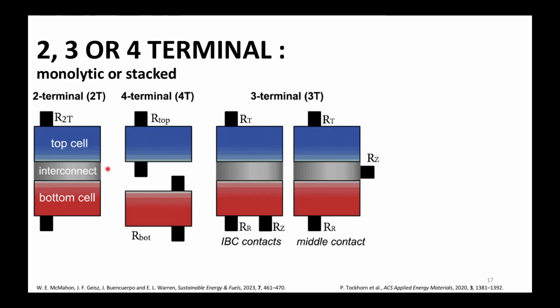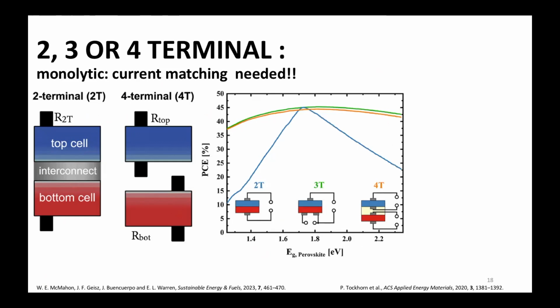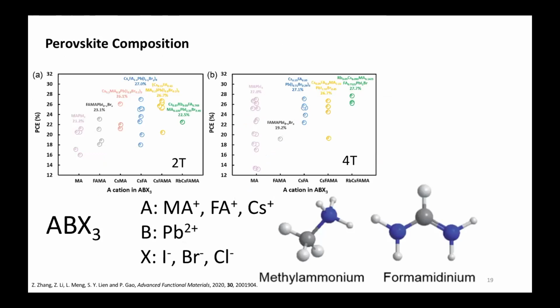The monolithic 2-terminal device is the most common or the most interesting, but it has a limitation. It has a limitation because you need to have current matching. If you take a 4-terminal or a 3-terminal device, it doesn't really depend on the band gap. The maximum efficiency that you can get doesn't really depend on the band gap. For the 2-terminal, you really have to be at the optimum. So you have to be at 1.7 electron volt. Otherwise, your efficiency drops because the two layers are interconnected by this recombination layer. We will get to that.